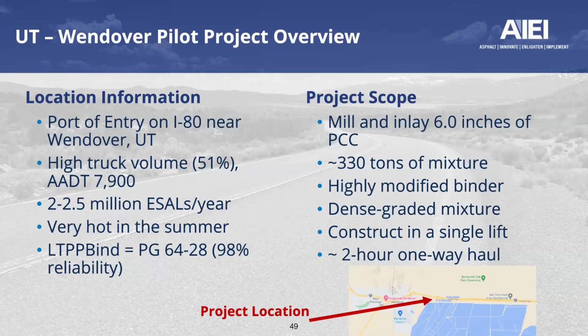The project itself is not a very high tonnage. This was a trial. Around 330 tons is all. It was an existing Portland cement material. They milled out 6 inches, and in one lift, they replaced it with this highly modified material. One of the reasons that this location was chosen, as I mentioned, is that it was one of the most challenging.